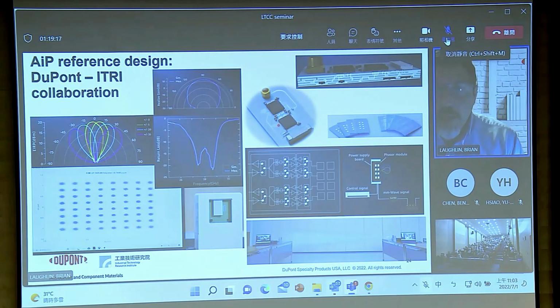And when you put in the mmWave chips and a full system to drive the mmWave chips to use their phaser capability, you can do beam steering minus 35 to plus 35 degrees with EIRP up above 18 dBm. And so we utilize the fact that there's very, very low dielectric loss and the ability of our 9K7 to make a fully integrated system to make not only a very high quality antenna package beam steering array, but if you look at the error vector magnitude measurement, so when you do the 64 QAM and look for your error data rate, we're below 1% data rate.